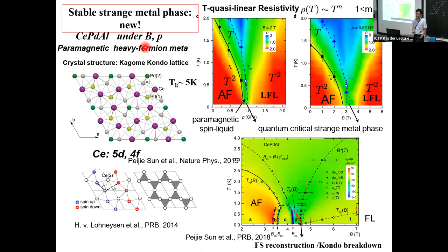So let's go back to the material that we focus on. This is a cerium palladium aluminum compound under field and pressure, and this is the heavy fermion metal, and the crystal structure looks like this Kagome lattice where the cerium atoms are sitting. The cerium carries 5d and 4f electrons, which could lead to the Kondo effect and also the so-called RKKY interactions, which I will talk about later. And as I showed you, the transport properties show this extended region of quasi-linear resistivity. But at the same time, at the end of this paramagnetic state, there is a Kondo breakdown transition, which I will talk about in just a moment.